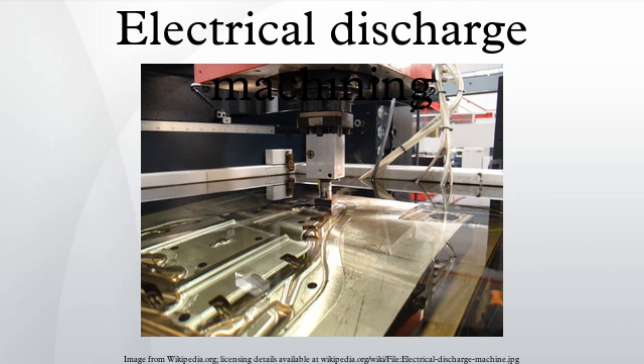EDM drills bore holes with a long brass or copper tube electrode that rotates in a chuck with a constant flow of distilled or deionized water flowing through the electrode as a flushing agent and dielectric. The electrode tubes operate like the wire in wire-cut EDM machines, having a spark gap and wear rate. Some small-hole drilling EDMs are able to drill through 100 mm of soft or through hardened steel in less than 10 seconds, averaging 50% to 80% wear rate. Holes of 0.3 mm to 6.1 mm can be achieved in this drilling operation.